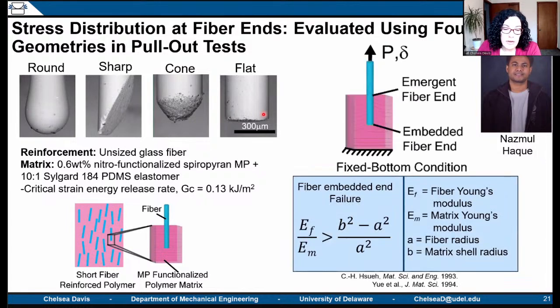And he was really careful to follow some of the analysis that already exists in literature from the 90s in order to ensure that in all of his experiments the failure event occurred at the bottom of the fiber, or the embedded end, rather than at the emergent end and then having the matrix just unzip from the top down. And he's performed all of this analysis to ensure that his geometry and modulus mismatch between fiber and matrix was such that we always get embedded fiber end separation.